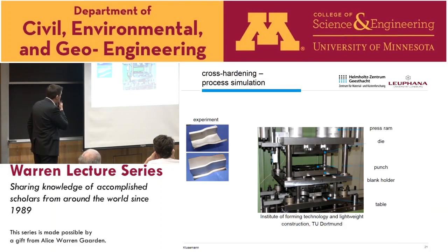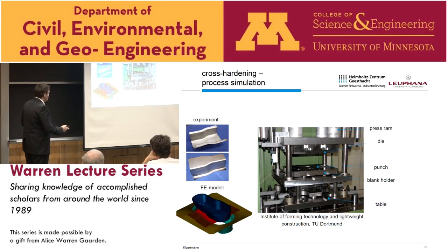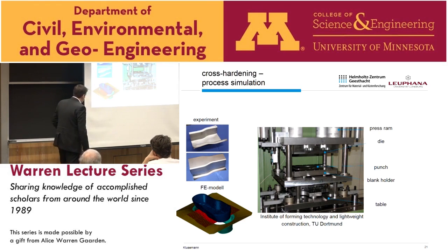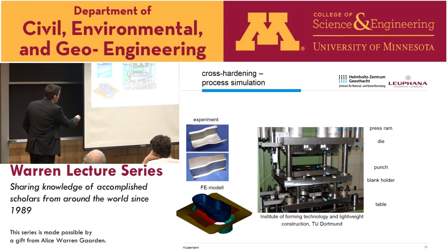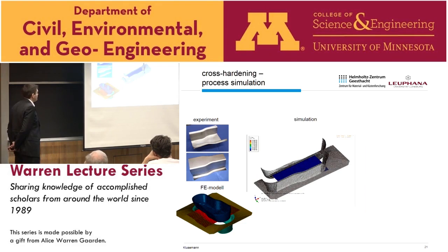So we did that. Let's continue. Yeah. So we did this with an experiment which was done at the Institute of Forming Technology and Lightweight Construction at the Technical University in Dortmund. So in principle, a deep drawing setup, and this was our demonstrator, how it looks like. We have different curvatures, different radii to have a good comparison for the modeling. So we set up, of course, our finite element model, which accounts for the die, for the matrix, and also we applied the correct force to keep the blank in place, to account for the blank holder force, to account for the correct flow inside of our specimen.